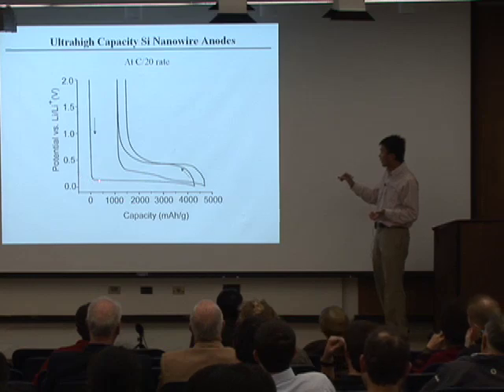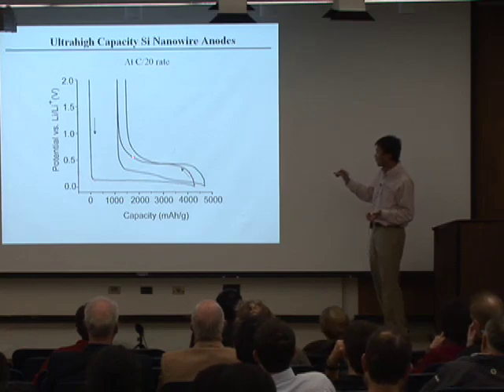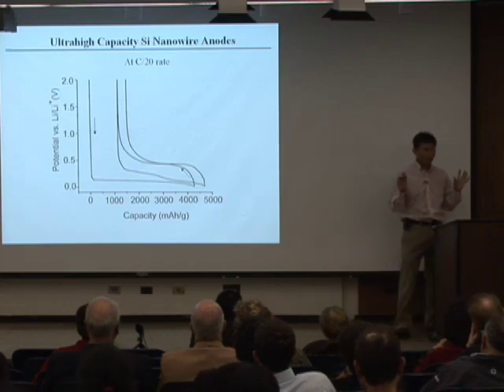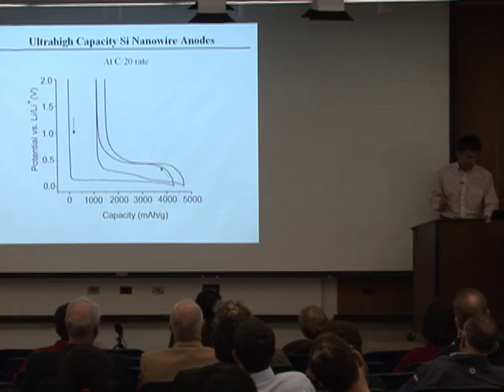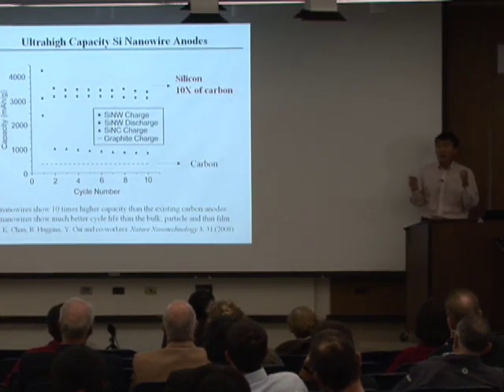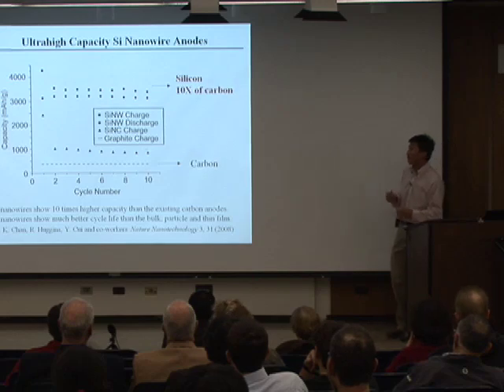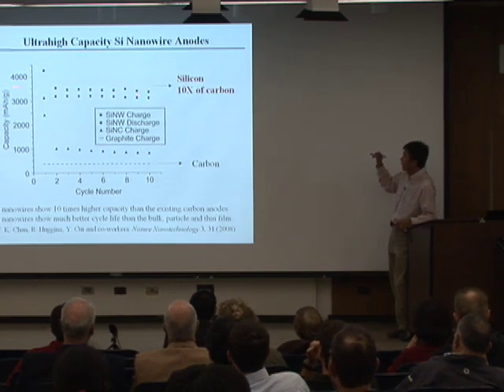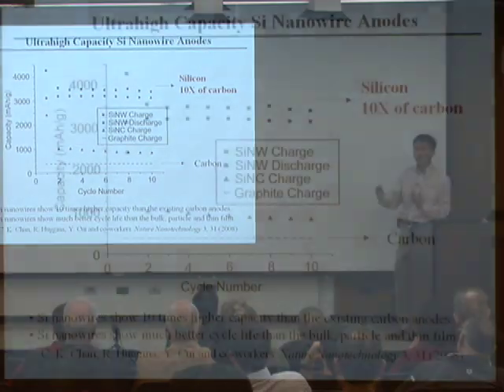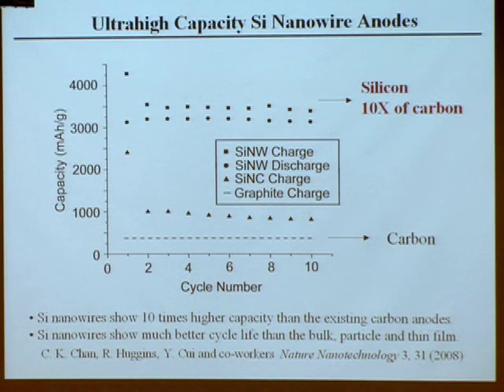So the potential shows a plateau, and you discharge this and charge it again. So this allows you to calculate the capacity. In the very early days, this is almost the first set of data we produced. We can go up to extremely high charge storage capacity for multiple cycles. Now, this is silicon nanowires. This line right here is carbon. So we produce about 10 times the carbon charge storage capacity. That has been very exciting.